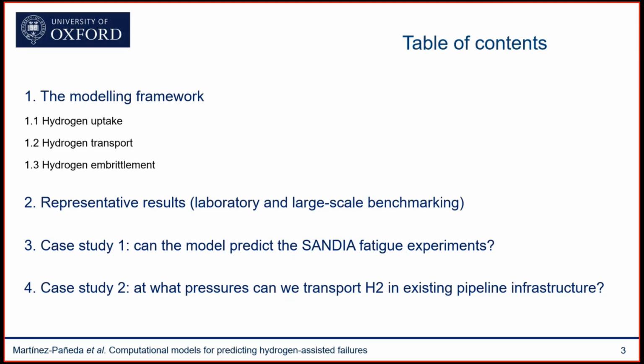And then the second one is that, as I said before, there's a lot of discussion on whether we can transport hydrogen in existing pipeline infrastructure. And there again, of course, the critical problems related to welds, which are typically the weakest link within that pipeline infrastructure. So we will use the model to show whether we can deliver predictions on what's the critical pressures that we can transport hydrogen in those pipelines.